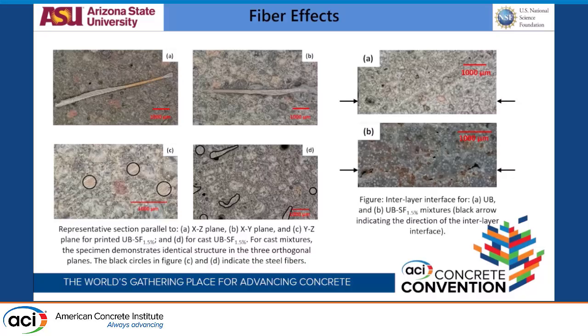But if you see the fourth image D, it's for a cast sample. If you cut a random section, be it along the length of the beam or perpendicular to the beam, you will see some circular, some elongated, some weird-shaped steel fibers because they are randomly oriented. There's no particular orientation to it. So this basically tells us why the 1% performs better. But why did the 1.5% not perform as well compared to C? Because there should be fiber orientation in those also.